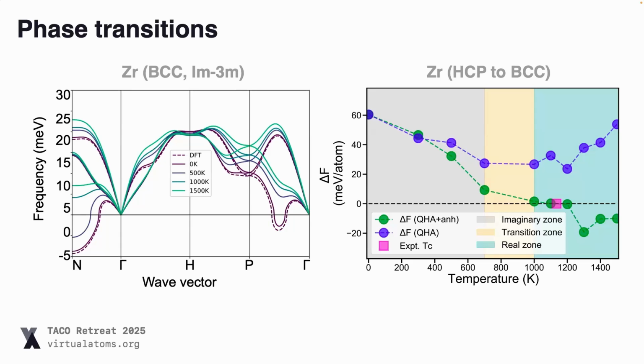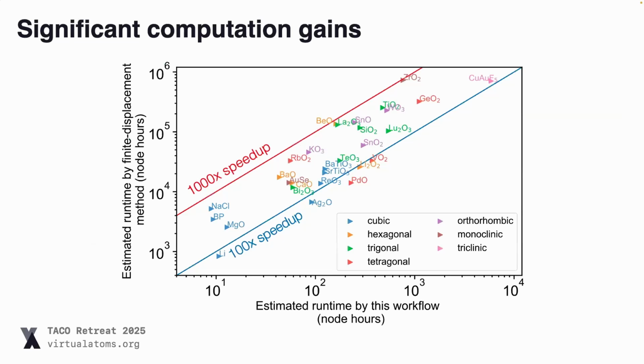So this is one thing we want to move towards now with this sort of approach, being able to calculate temperature-dependent phase diagrams. And so there's a lot of scope for us to do that based on the speed of these calculations. And just to highlight the speed, this is looking at the speed up that we would gain compared to Phono3py, or compared to the naive approach of calculating all of the force constants. For most materials, it's at least 100 times speed up, and for some materials, it's close to 1,000 times speed up compared to the naive approach. So we really do save a lot on computational efficiency.